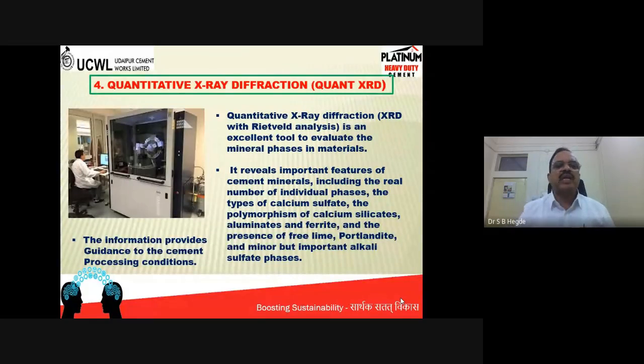And when you are analyzing the powder material through XRD, it will try to match the 2 theta values of all these 50,000 phases stored in the JCPDS file, and then it will give you the probable minerals which are present in your powder. So this is a very stringent analysis which takes around, depending upon the scanning speed of your run. For example, if I give 1 minute per 2 theta degree, it may take to scan from 2 theta to 140 degree 2 theta maybe around half an hour or 1 hour, depending upon the steps and speed I have set in the system for scanning.